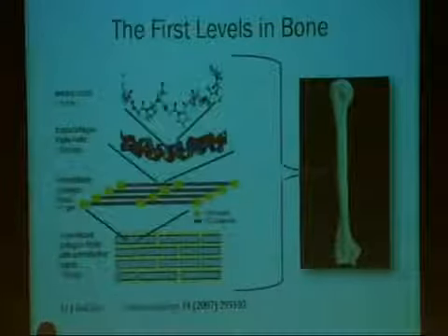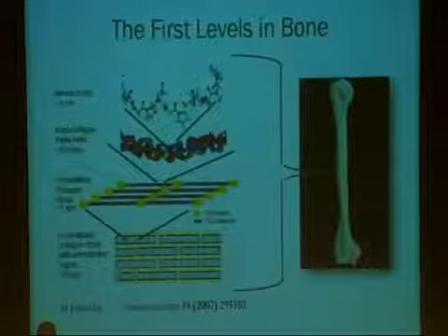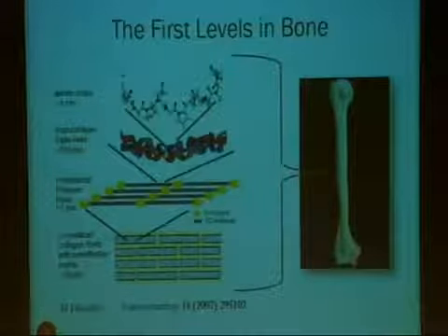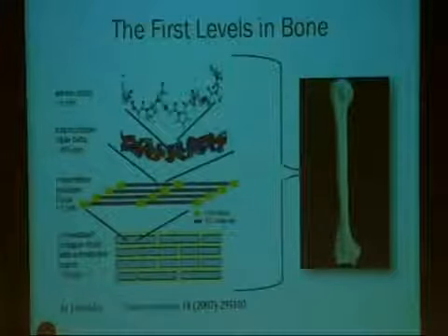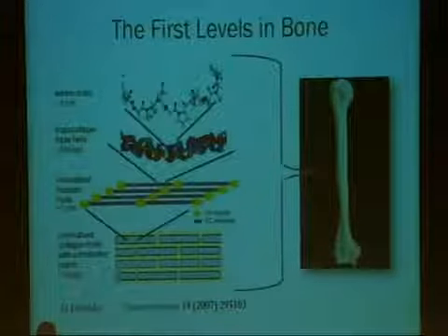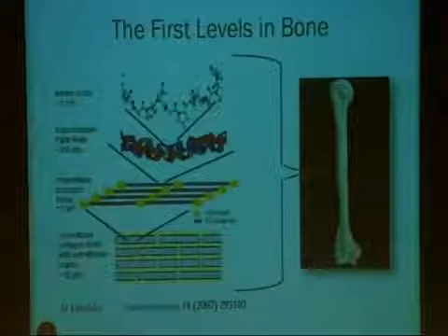The reason we're studying different thicknesses is because there are different stages in bone, sometimes with hydroxyapatite that is thinner and hydroxyapatite that is thicker. We want to study whether, for the thinner model, it's not only the density, the amount of hydroxyapatite, but maybe the thickness of it that matters, because previous models only tested the density of the mineral.